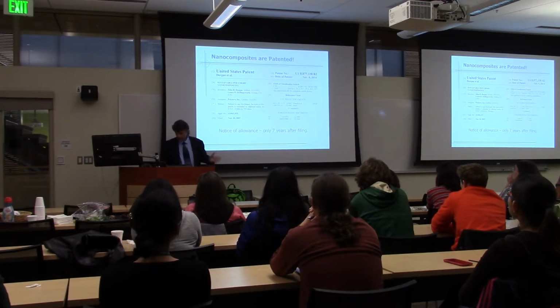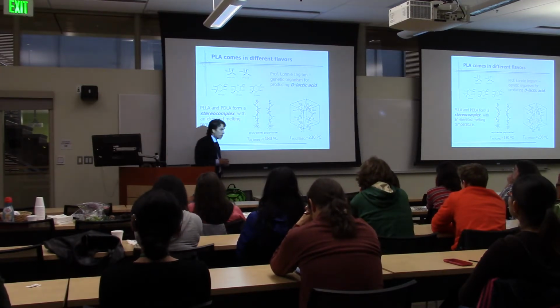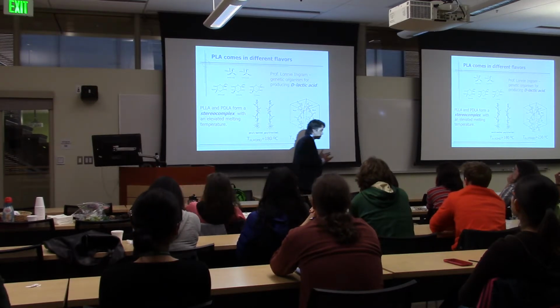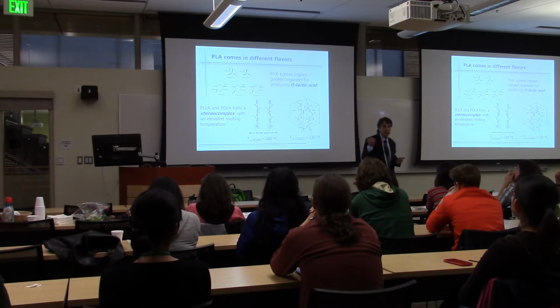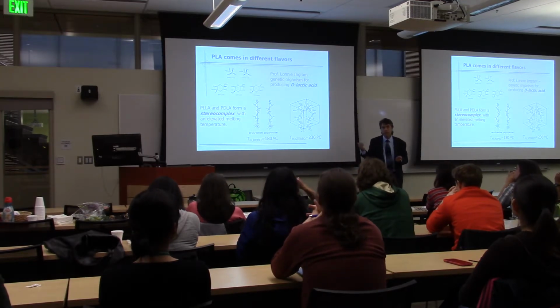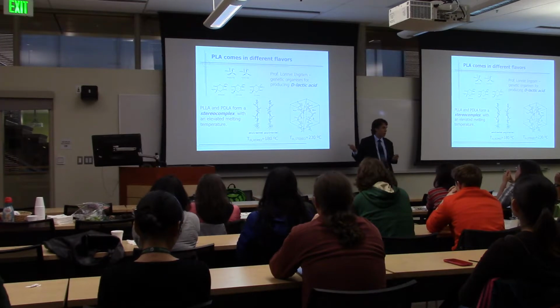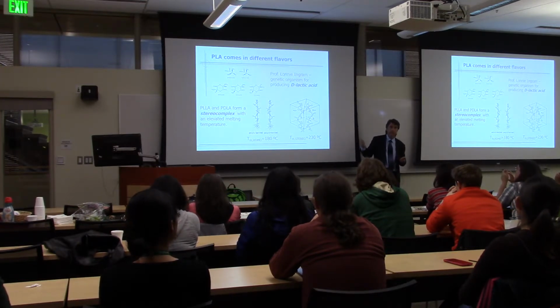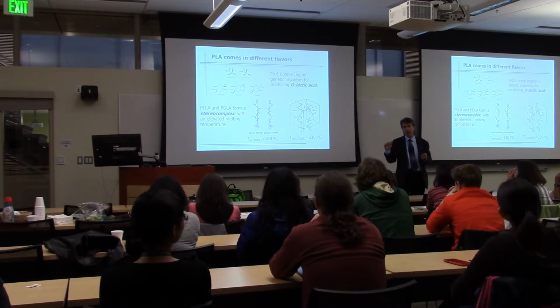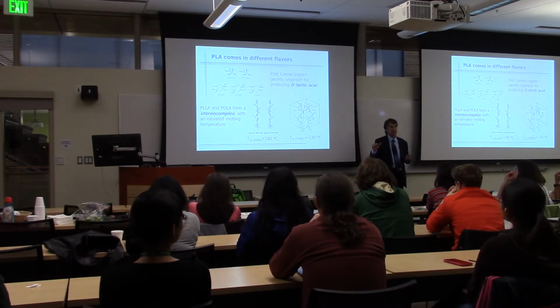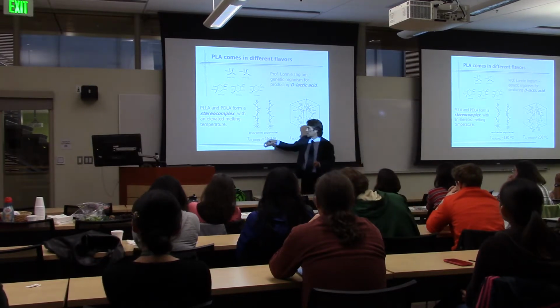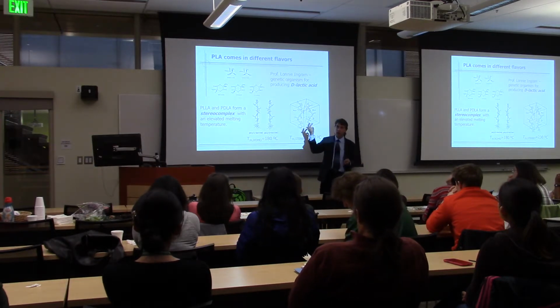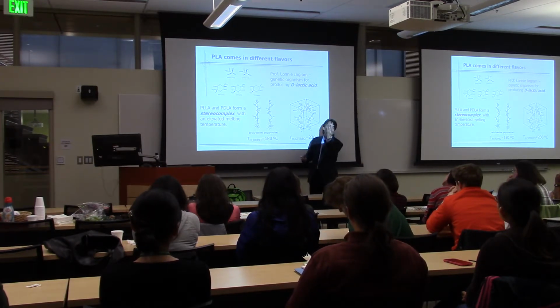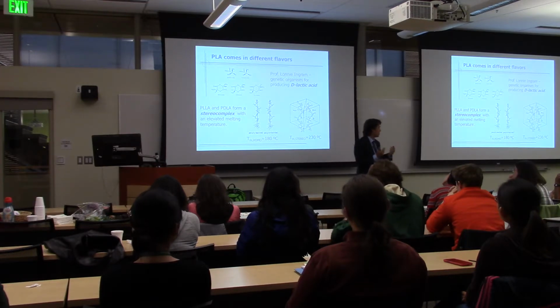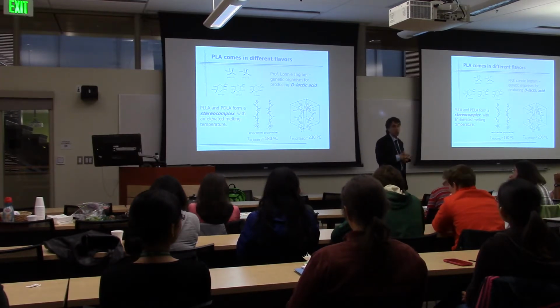So patented that. I alluded early on in my talk to the importance of being able to control stereochemistry. And in polylactides, that's particularly important. That's because, as I said, with the genetically modified organisms, we can now make the D-lactic acid and the DD-lactide. Well, it turns out the handedness in the monomer actually translates itself into handedness in the crystallization. If we look at the way polylactide crystallizes, the all L material will crystallize in a right-handed helix, and the all D will crystallize in a left-handed helix. And so we have a unique phenomenon known as stereocomplexation.